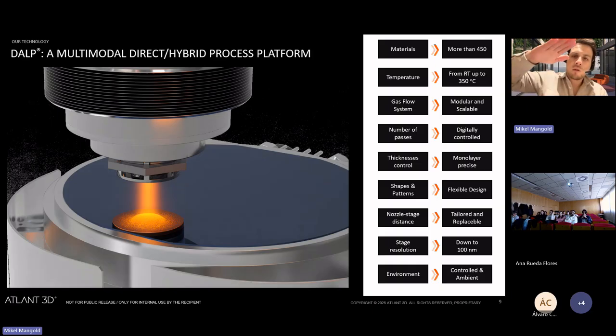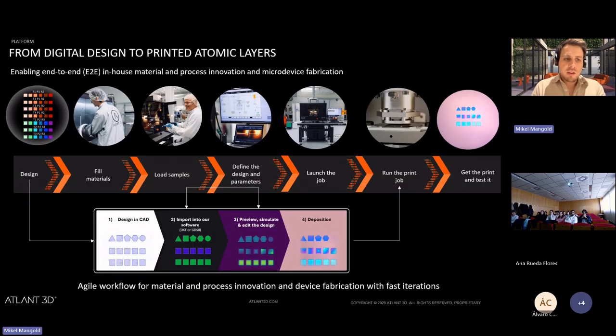So if we put the nozzle close, we're going to get ALD, and if you put it a little bit higher, you will get some kind of CVD deposition. So we can even modulate that. So this is how it works.